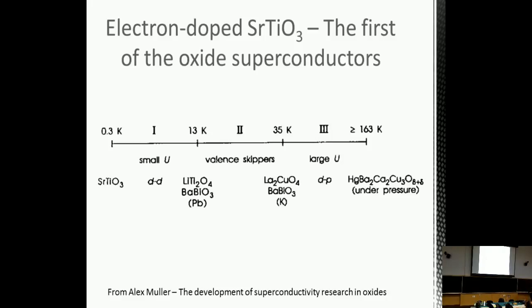So strontium titanate was the first of the oxide superconductors discovered in the 1960s. This comes from Alex Muller's development of superconductivity research in oxides. And the superconducting transition temperature is less than 1 Kelvin, quite low. And then that led to a development of perovskite oxide research, ending up with the high temperature copper oxide superconductors.